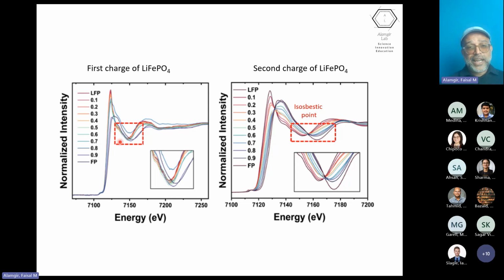In the first cycle, because there's a bunch of separate reactions happening, those pinch points cannot manifest, and so it looks, let's say, haphazard. The data looks more haphazard, but it basically gets cleaned up by the second cycle. So that mere fact that we don't get the isosbestic points in the first cycle tells us that all these side reactions are happening. If we get the isosbestic points in the second cycle, it means that majority of them have already completed, to the extent that we are getting essentially a single reaction from the second cycle on.